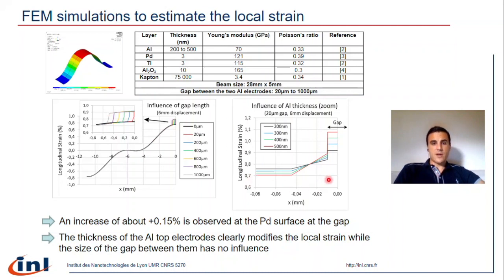Here on the right, we have studied the influence of the thickness of the aluminum top contact on the local strain. As you can see on the graph, by increasing the thickness of this aluminum top contact, we can increase significantly the local strain and facilitate the crack formation. So by playing on the thickness of this electrode, it is a way to localize the cracks and facilitate the crack formation process.